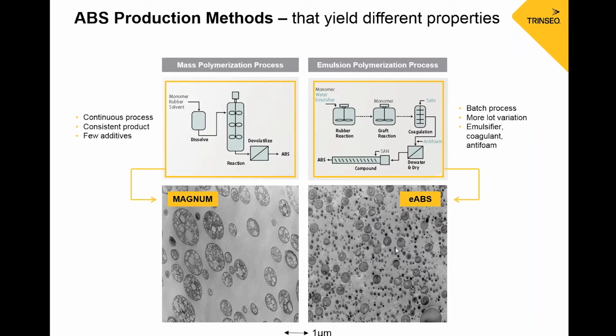The emulsion ABS have historically been more used in those applications because the rubber particle size itself plays a very large part in producing that high gloss. But with the mass ABS, depending on the agitation and the rubber content, we can get the rubber particle size to be different. We have a wide range of production methods that we can use, and we can get really low gloss, and we can get to a high range of gloss, but not quite as high as what you see with the emulsion ABS.